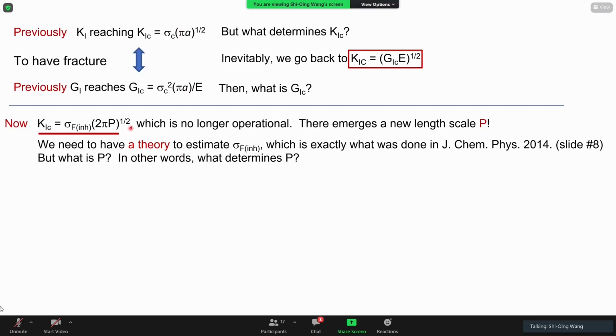Now, what we learned through playing with this birefringence to learn about the stress buildup at the point of fracture, we learned that the Kc actually has some dependence on the material properties. In fact, we are explaining why Kc is a material parameter, because the inherent strength is a material parameter. And this P is a natural length scale that comes into the problem when you prepare a cut in the sample. So it's in that sense, when we are dealing with glassy polymers, we have already dictated that your Kc will be more or less a constant, not going to change very much. But of course, Kc for glass is very different because the P will be very small. For example, for glass, it will be nanometer scale.